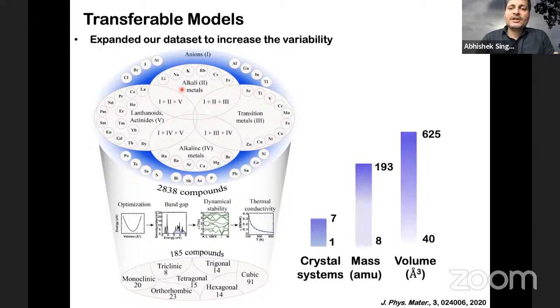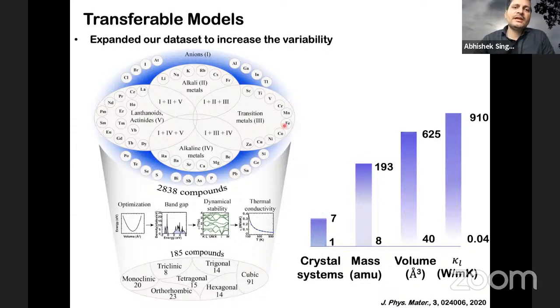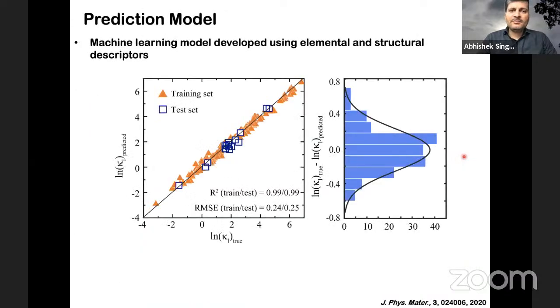So one way of doing it is to make your database have as much variability as possible. For example, we extended our database and created a new database wherein we have all the crystal systems from 1 to 7, mass varies from 8 to 193. So these are my feature spaces. Volume can go all the way from 40 to 625, and the thermal conductivity varies by almost 4 or 5 orders of magnitude. So this has a huge amount of variability. And we created a model, yet it was an okay model, but not a very good model. Okay, so how do we get there?